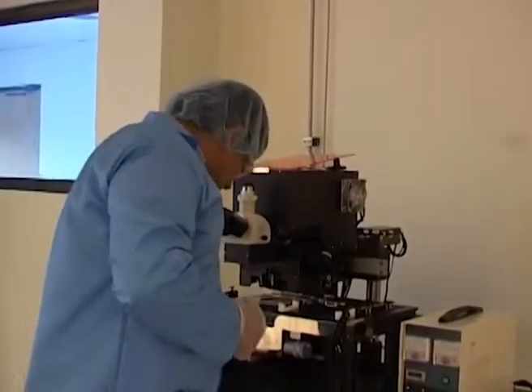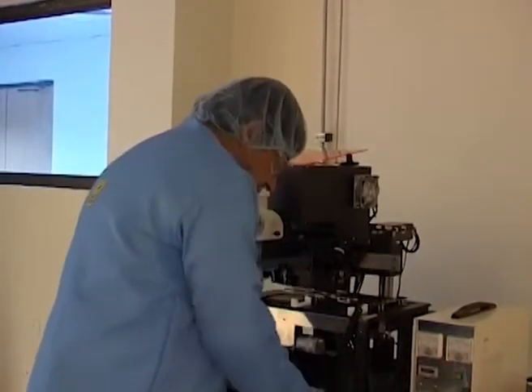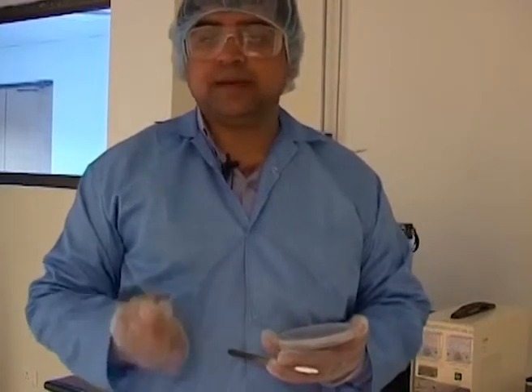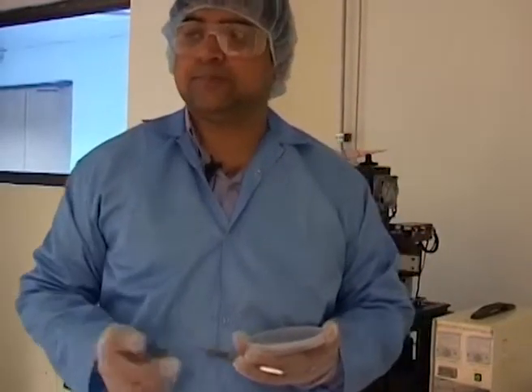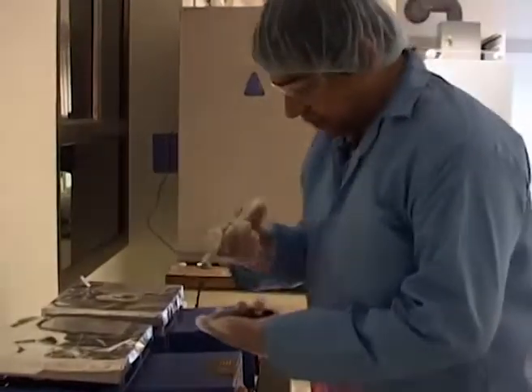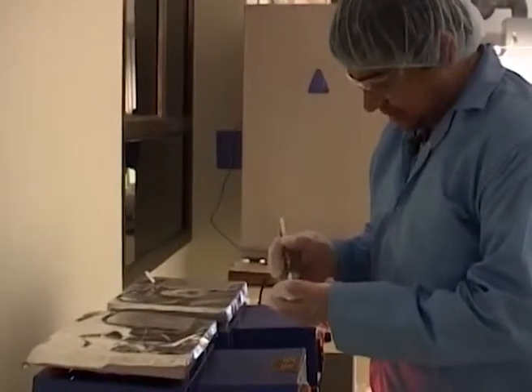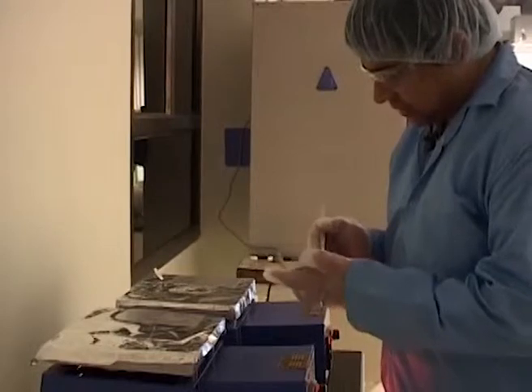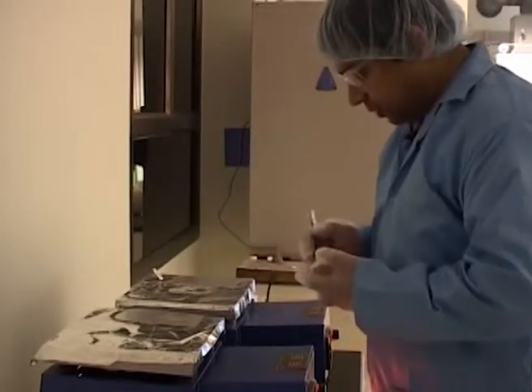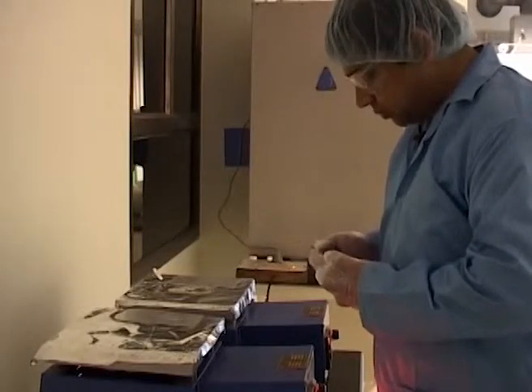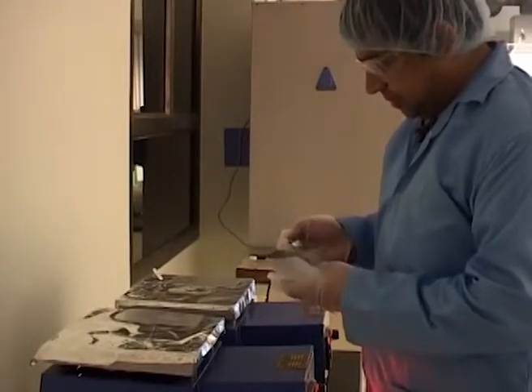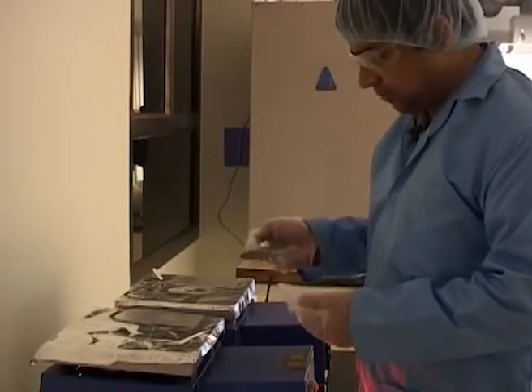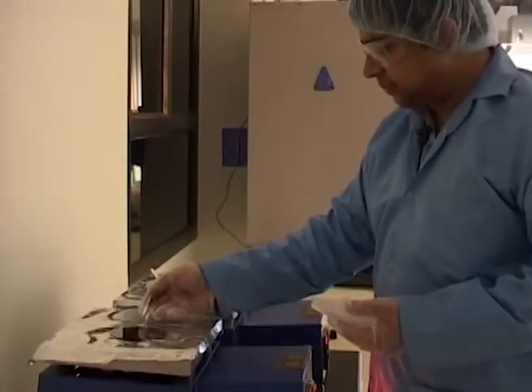And so doing this, what we really need to do is to take this wafer back to our heating station, and there are again manufacturer specifications of the resist which talk about how many minutes we need to post exposure heat or bake this using the hot plate at the two temperature conditions that we had done before. So I'm going to now pull out this exposed wafer coated with photoresist as we did in the last step, and slowly place it on top of this hot plate, and the time that we allow it to be heated at the 65 degrees step is about 1 minute.